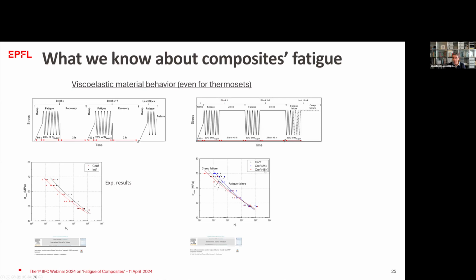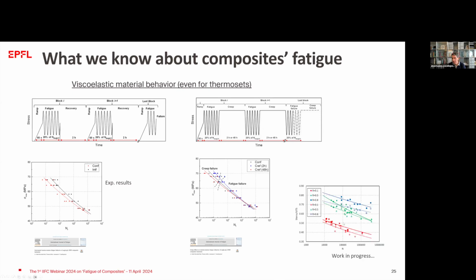But when we introduce long creep components, so creep loads for longer times, we've seen that the behavior has been worse. So the lifetime has been decreased exactly because the creep was dominant in these loading cases. What we are trying to do now is to investigate also the performance of the material, to see this effect of the viscoelastic performance of the material on the fatigue life. And this is work in progress.